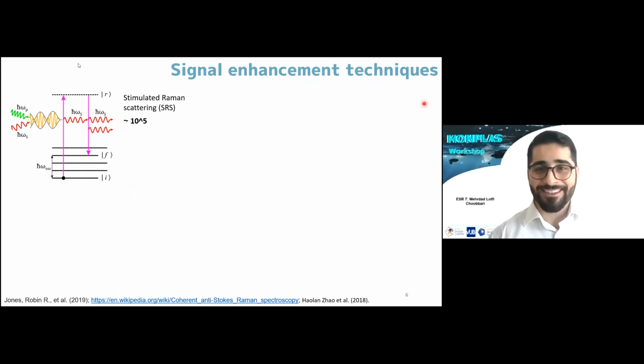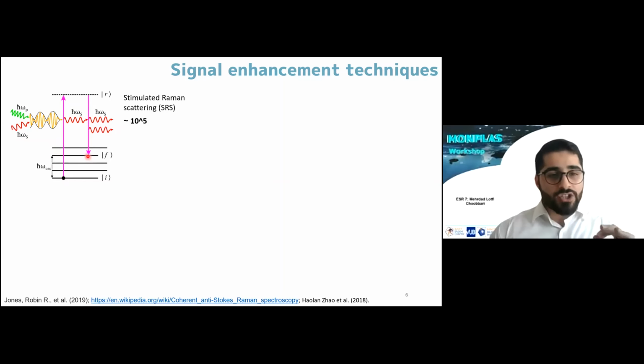It's not minimizing, okay. The first method which I'll talk about is stimulated Raman scattering, which can be used to enhance the signal of Raman scattering. In this method, we use two sources of light to excite the molecule, and we adjust the energy difference between these two sources of light in such a way that this energy difference matches the energy difference between the rotational vibrational states of the molecule with respect to the ground state. And therefore, this can stimulate the process of Raman scattering and enhance the Raman signal up to 10 to the power 5 in comparison to the conventional Raman spectroscopy.